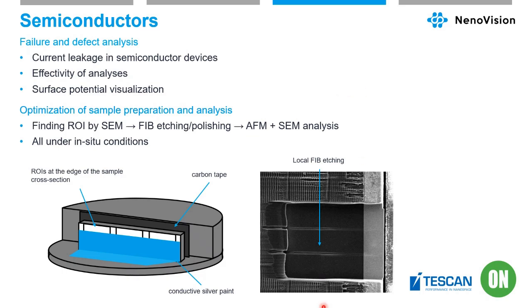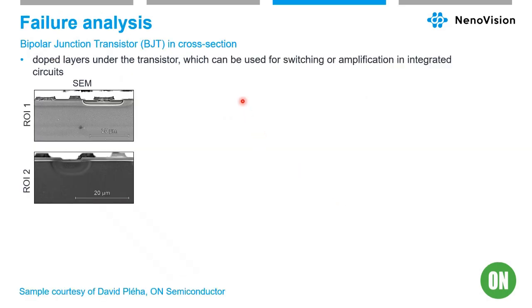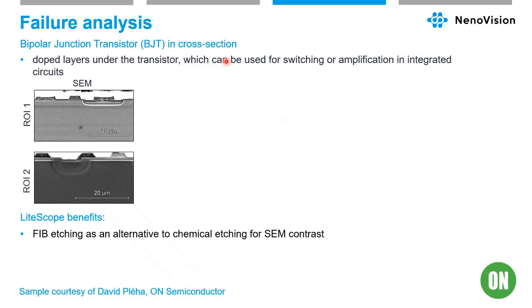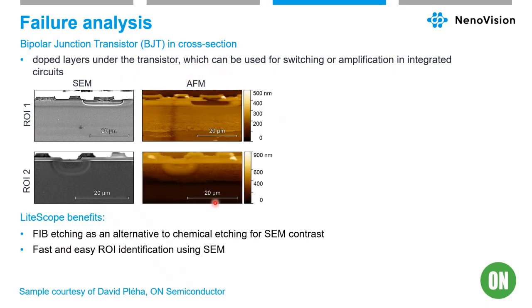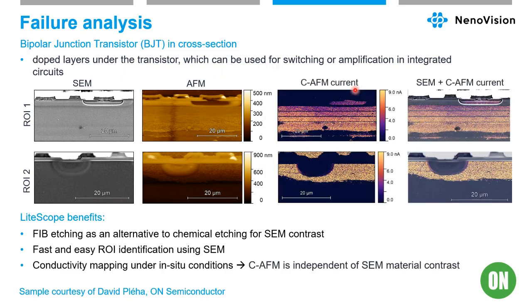So I have an example of a bipolar junction transistor in cross-section. We see that there are doped layers under the transistor, and these can be used for switching or amplification of integrated circuits. And so if we measure SEM and the AFM topography together and combine it with the conductive AFM, we see that there are different layers, more or less conductive, and not always is it connected to the topography.